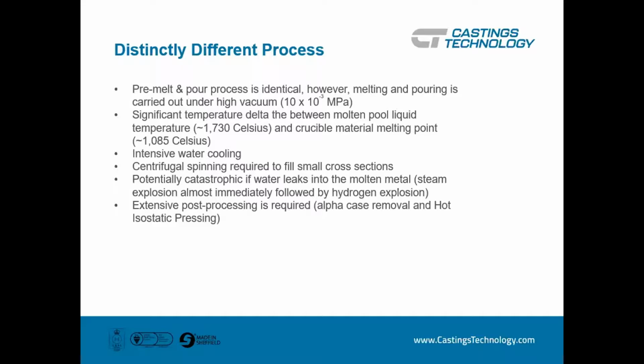We have a significant temperature delta between the crucible we're melting the titanium in, which is made out of copper, and the titanium itself. And as you can see there, it's a differential of some 650 odd degrees or just under. So we have a lot of water cooling, which runs constantly around the copper crucible, goes outside to heat exchangers and comes back in the building. And all the while we're centrifugally spinning some fairly fragile shells, which could weigh several hundred kilograms each, spinning at 20 G. So there's a lot going on in there when we're melting titanium.